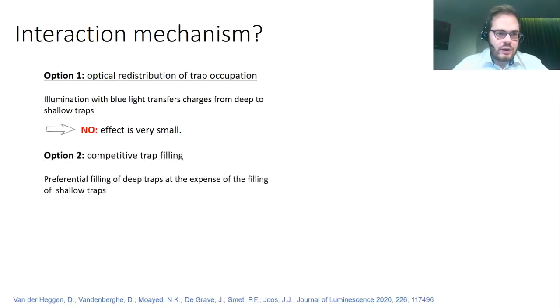So the second option is the option of competitive trap filling, and that when we switch on the excitation source, there is competition between the deep and the shallow traps to be filled, and that there is actually preferential filling of the deep traps at the expense of the filling of the shallow traps.